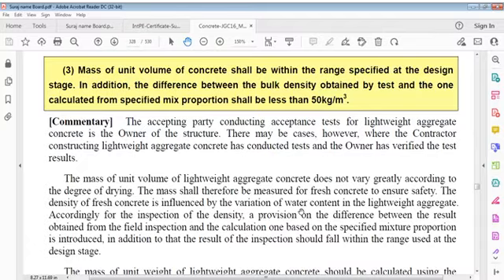Difference between bulk density obtained by test and one calculated from specified mix proportion shall be less than 50 kg per meter cube. What it says? Mass of unit volume of concrete shall be within the range specified at design stage. In addition, the difference between bulk density obtained by test and one calculated from specified mix proportion shall be less than 50 kg per meter cube.